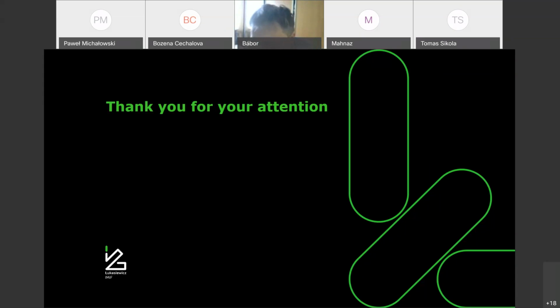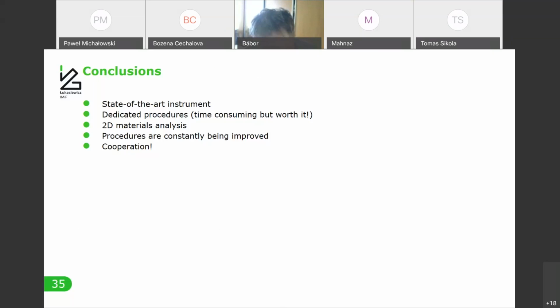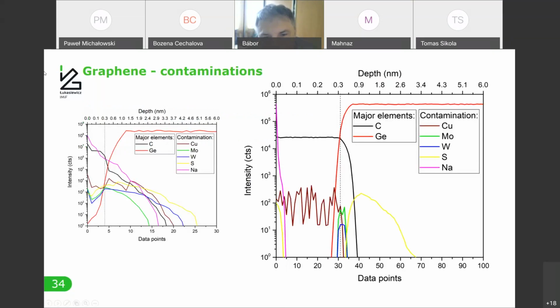Sure. Okay, maybe I will show a few things. So I will start with this one. The left profile, pretty often the drawback of this procedure is the analysis time. The left profile took 5 minutes to get, and the right one is 3 hours. Roughly the same depth. Okay, the depth calibration is just for estimation. So here I sputtered 6 nanometers for 5 minutes, and here 6 nanometers for 3 hours. So the difference is huge. So basically the integration time of these signals is much higher than in the other ones.